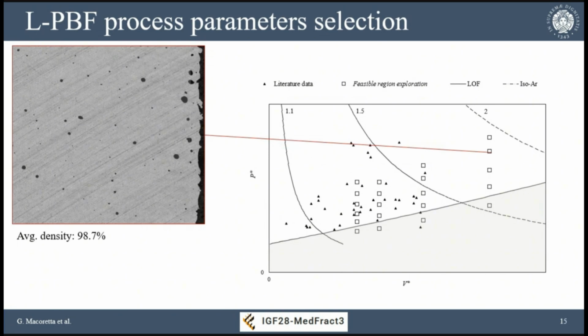When we increase the velocity and power a lot, humping phenomena start occurring—local instabilities of the molten pool that can create seldom, randomly occurring pores due to instabilities, because we are greatly increasing the aspect ratio of our molten pool.